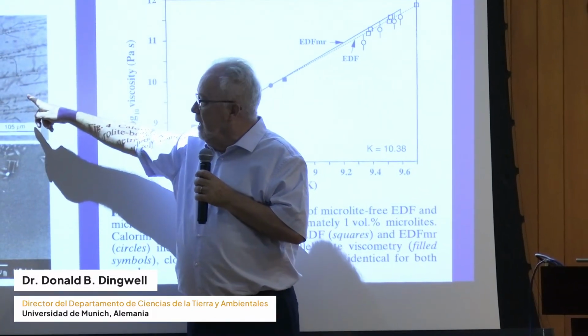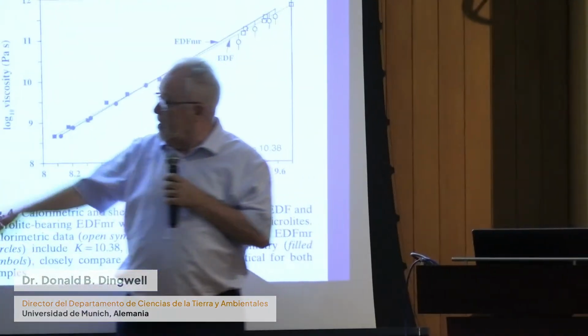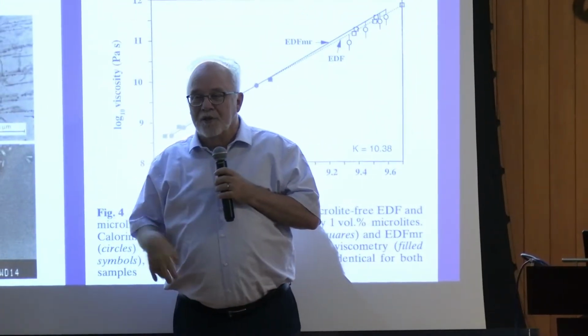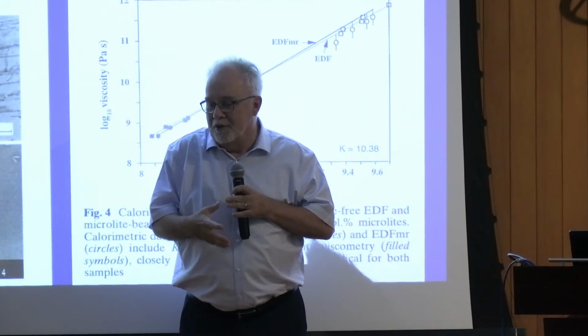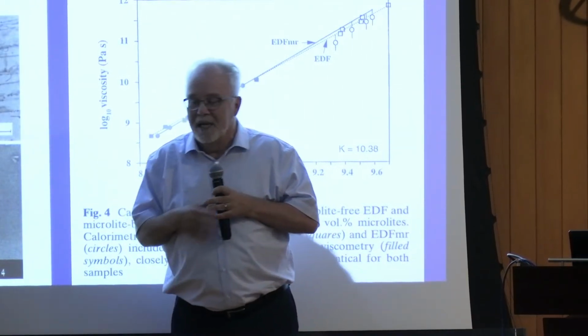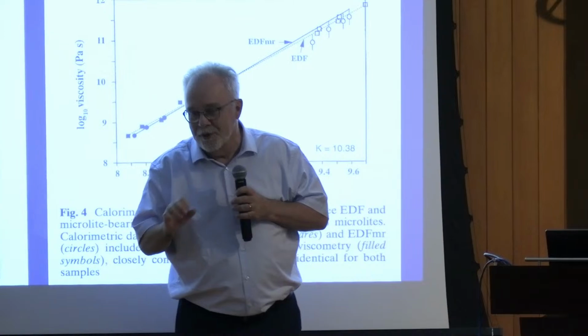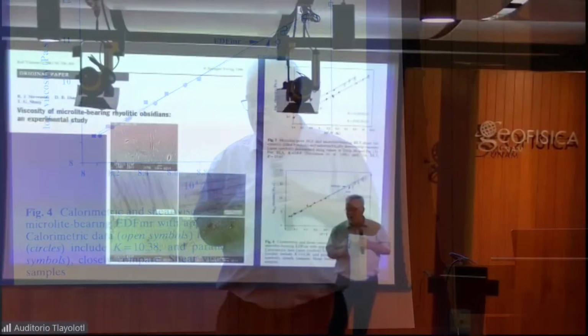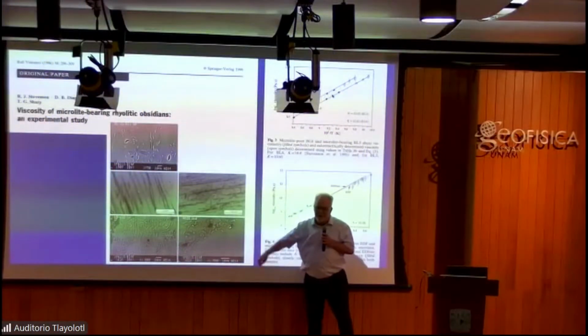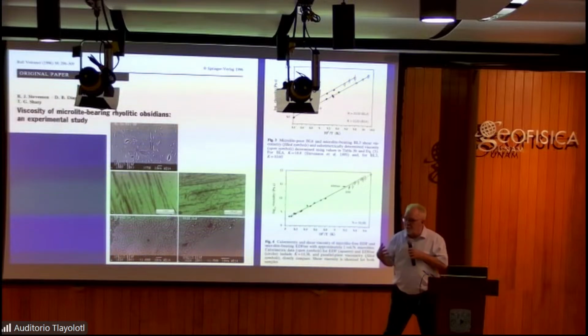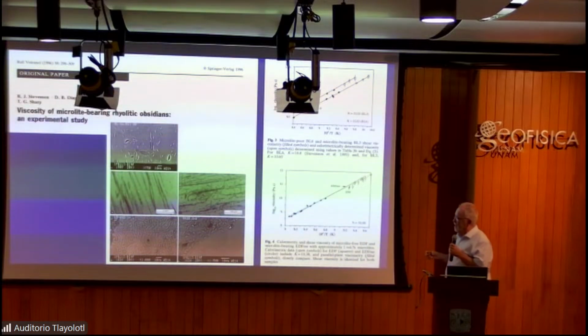Or try to synthesize this chemistry of this glass so that you have a crystal-free sample, and then you can calibrate. It's also impossible because your slight errors in the chemical synthesis of the glass are going to be enough to swamp the difference in viscosity. So how can we say what the effect of these microlites is on viscosity? We use calorimetry.